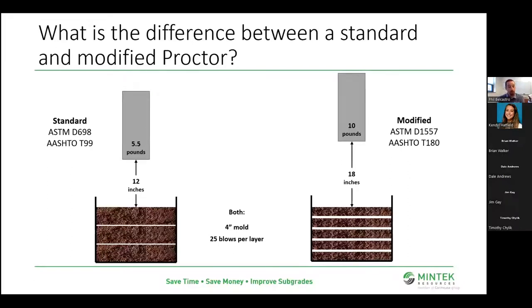One thing I want to point out again is moisture. The modified proctor usually results in a lower moisture requirement, so it's important that you still properly hydrate any material we put in there. Really, what we would do is treat with our lime above optimum and let it dry back to where it needs to be. That's in our lab, those great conditions, but it's important that we properly hydrate that material because we've seen proctor pills that clearly have unhydrated lime all over them when they fall apart. That's not the way to go, because we want to make sure we're repeatable.